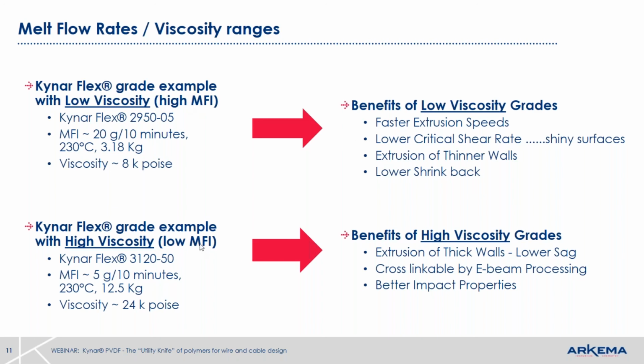On a high viscosity or low melt flow rate material, the benefit of that high viscosity is that you can extrude a thicker wall. So typically a chemically resistant type cable would require a thicker wall. So by using a high viscosity material like the Kynar 3120, you'll be able to achieve that. Also, most cables that are cross-linked also use a thicker jacket. So this high viscosity material would lend itself to that. And from an impact point of view, thicker is better. So if you're looking to have a dramatically strong, impact resistant material, I would go with a thicker jacket.